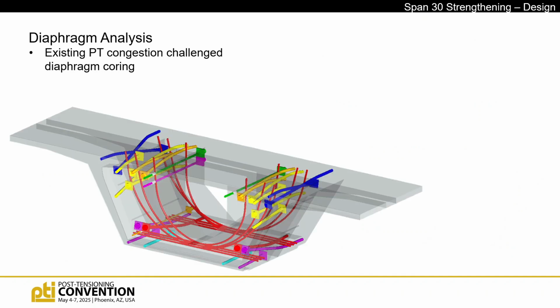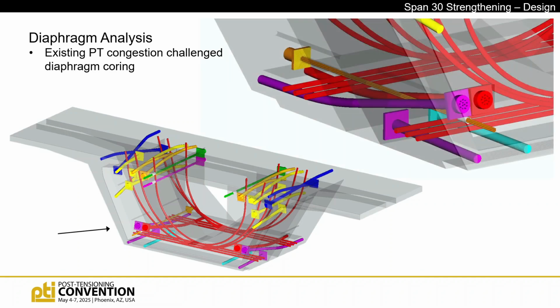All right. This is the congestion we're dealing with inside that diaphragm as far as the post-tensioning. The top slab transverse PT I didn't show, but there's some more PT in there, but it's above where we were working. Our tendons are the green and purple in the top there with the anchors on the far side of the image, and then the orange below that on the bottom. So you see it's pretty well congested here, but this is really the one that had the pucker factor.